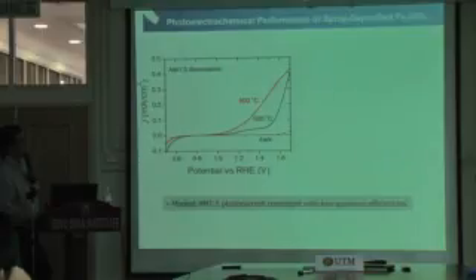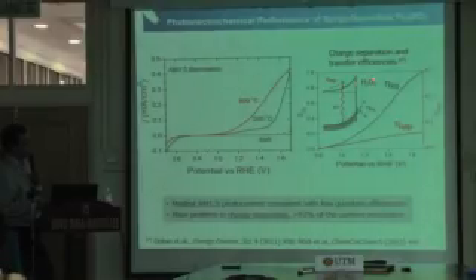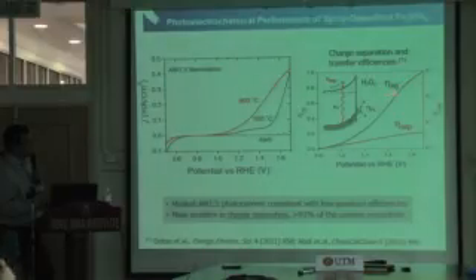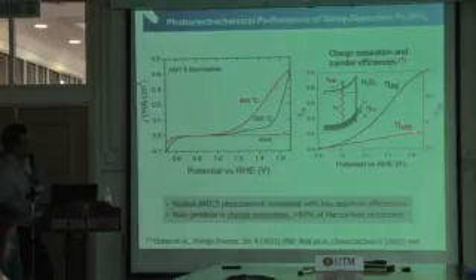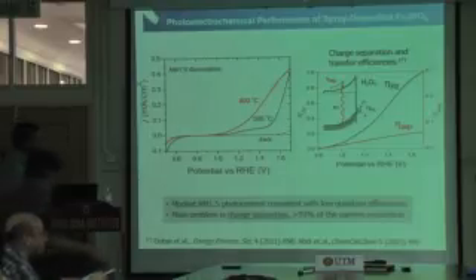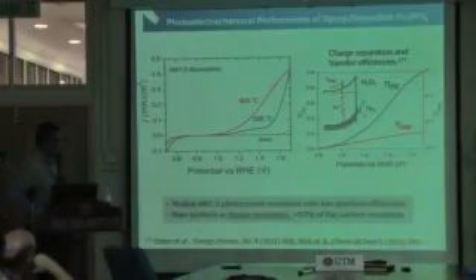Photoelectrochemical performance under AM 1.5 illumination is shown here. As you go from 500 to 800 degrees C, it improves, but only modestly, consistent with our low quantum efficiencies. We did the same analysis with the hole scavenger that I talked about at the beginning. We found that the carrier injection is low. This is the carrier injection, or catalytic efficiency. But we think that we may be able to work with this. But the carrier separation is amazingly low, only about 7%. More than 93% of the carriers recombine. So the main problem is really charge separation as well.